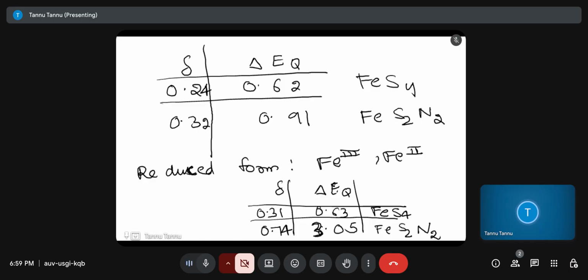So you can see now how with changes of valence contribution and lattice contribution, electric field gradients are changing. This is where you can see that even in the spectroscopic analysis of bioinorganic structures such as these clusters, ferredoxins, protein structures, etc., you can use Mossbauer spectroscopy to differentiate the ligand environment and what kind of cluster it is from unknown samples. You can also identify which cluster must be present in that sample.